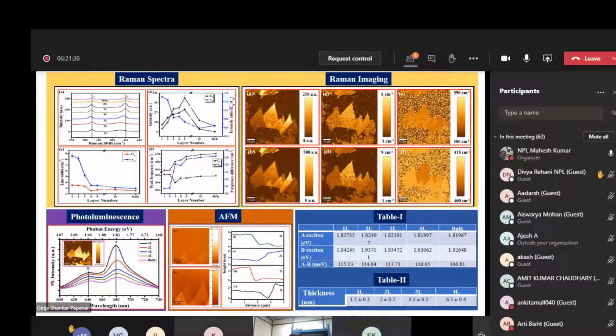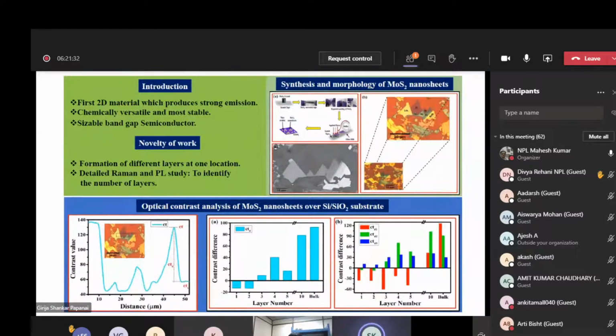So if you see the optical image, and you talked about the beam diameter, here we are using 50x magnification, and 1 micron is the spot size. And if you see this optical image and this location, at the edge of these two layers of MoS2, there is a difference of the substrate. So we only choose the layer where it has been sitting on the substrate, not behind this one.